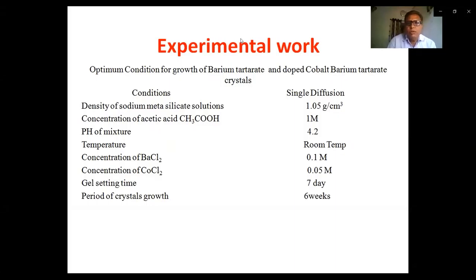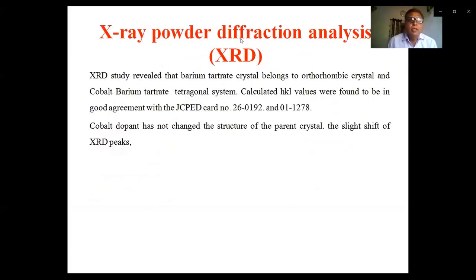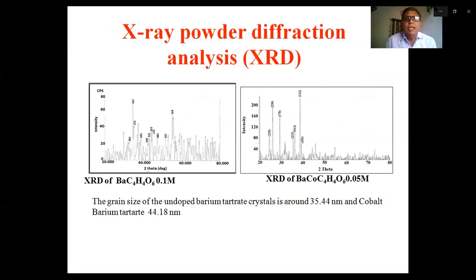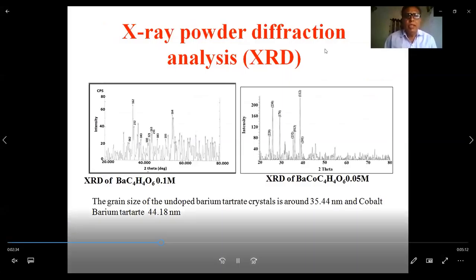The X-ray powder diffraction study reveals that barium tartarate belongs to the orthorhombic system and cobalt barium tartarate to the tetragonal system. Calculated d-values were found to be in good agreement with the JCPDS data, for barium tartarate 26-0192 and for cobalt barium tartarate 01-1278. Cobalt dopant has not changed the structure of the parent system, with only a slight shift in the X-ray powder diffraction pattern. Here I show the XRD of barium tartarate 0.1 molar and the XRD of cobalt barium tartarate 0.05 molar.